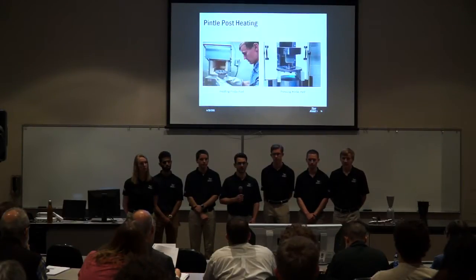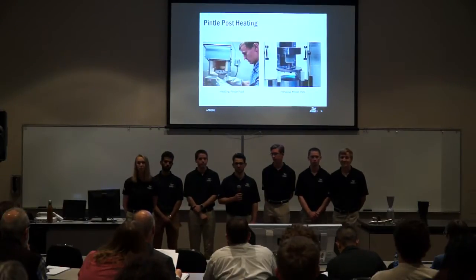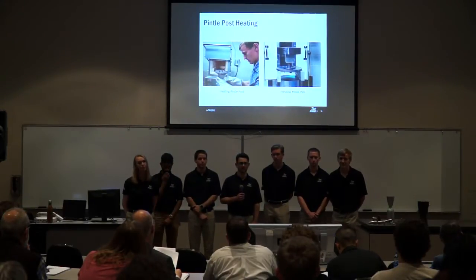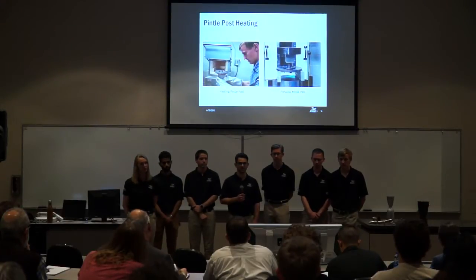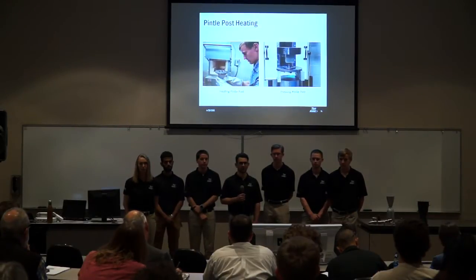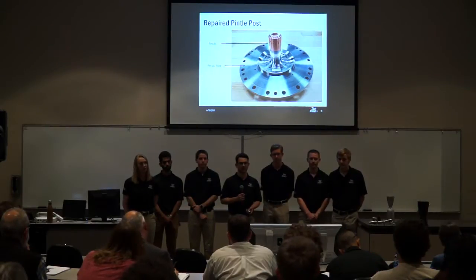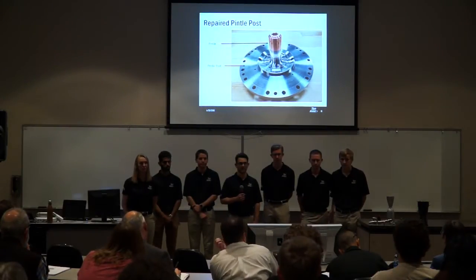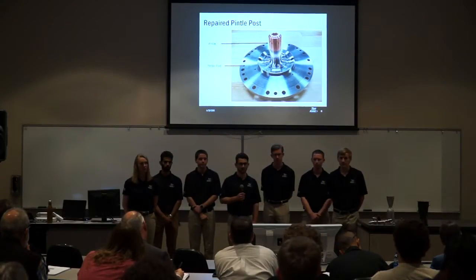And we did that by putting it in an oven and heating up to 1200 degrees Fahrenheit to reduce the residual stresses caused by the welding process, as well as it also reduced the yield strength. And so once that was reduced and it was hot, we then put it in a hydraulic press and pushed it back to nominal. Once we did that, it was nominal enough to where we could put it back into the lathe, and we were able to finish the final machining ops. Here is the finished product with the repaired pintle post and the pintle threaded onto it. You can see the drive tool on the pintle.